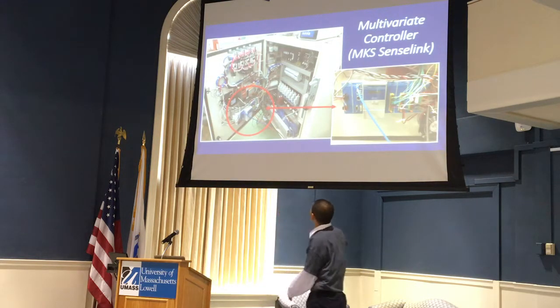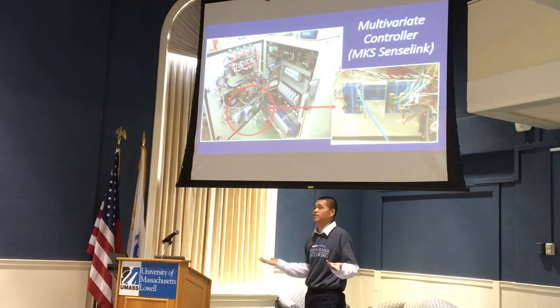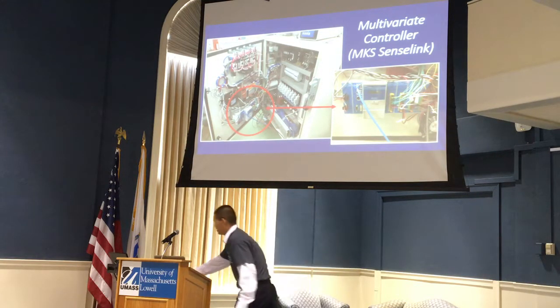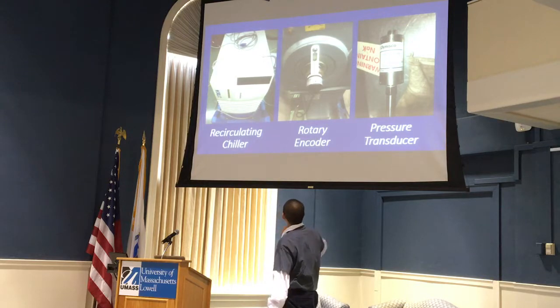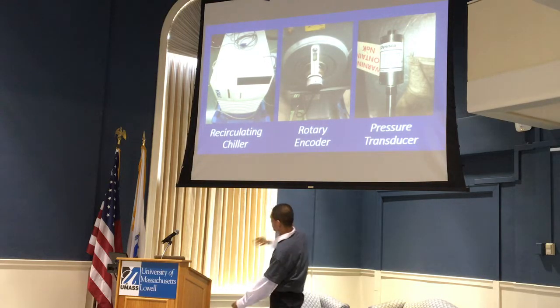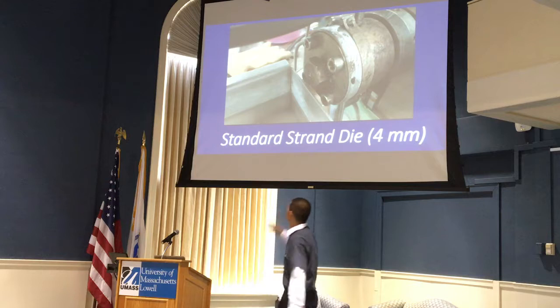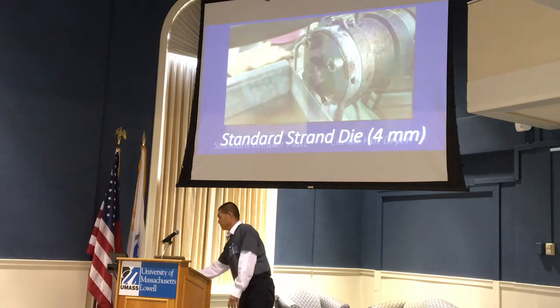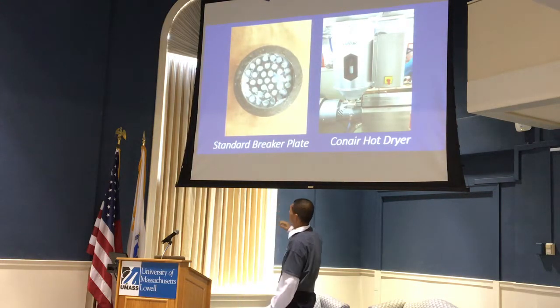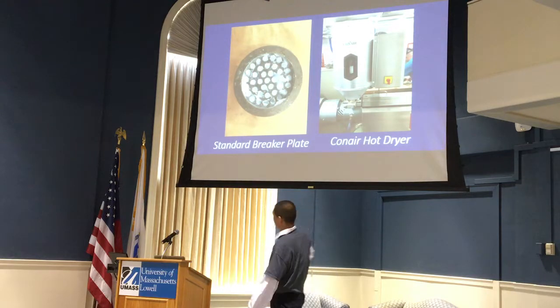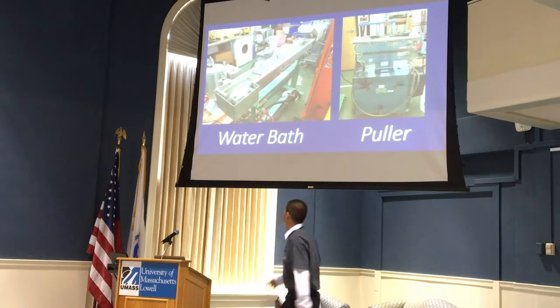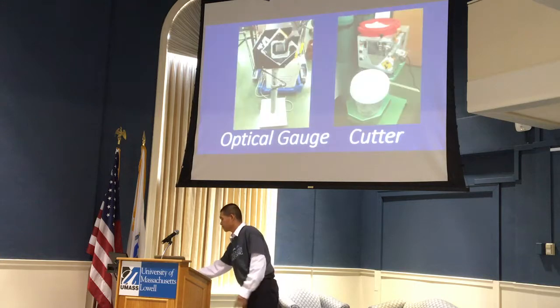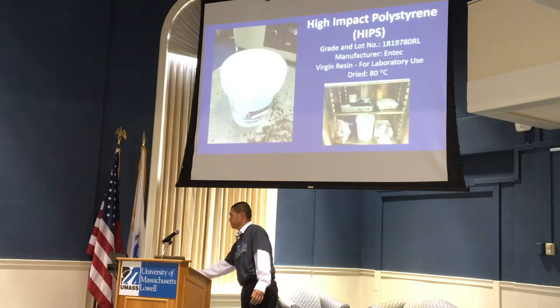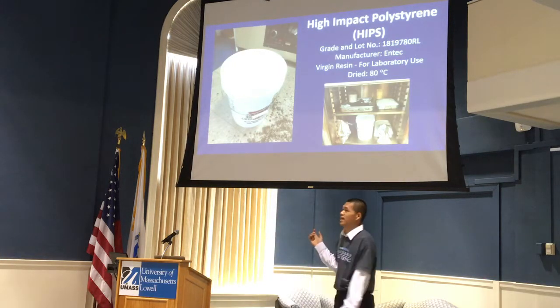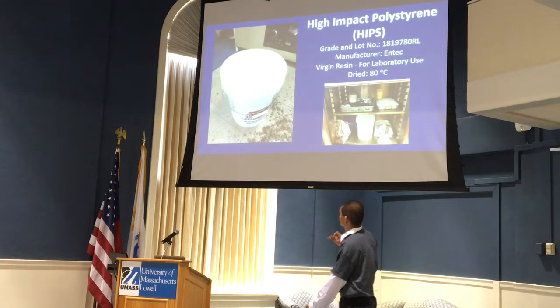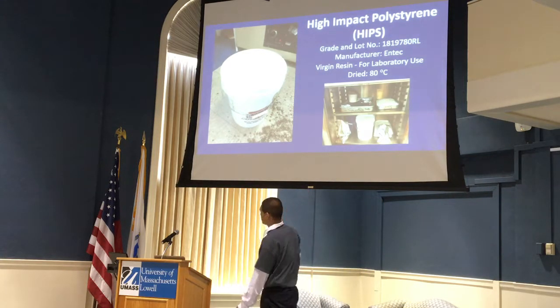We also have a multivariate controller, and this is how we acquire our data. We have our recirculating chiller, our rotary encoder, and a pressure transducer. We also had a 4mm strand die, a standard breaker plate, which Mike passed around, and a Conair hot dryer. We also have a water bath, puller, optical gauge and cutter. And we used high-impact polystyrene, which is an amorphous material. We dried it at 80 degrees Celsius.